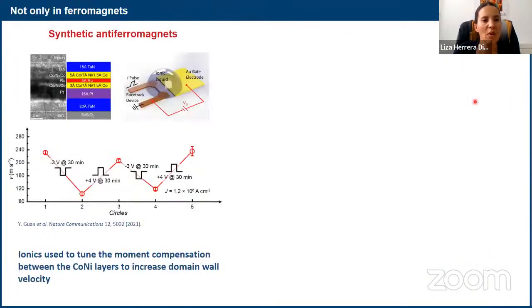Also another thing that is important to know is that this is not only in ferromagnets. We can find examples of magneto-ionic control in other types of magnetic systems. In particular, for example, here are synthetic anti-ferromagnets. This is done by a group in Halle. They showed before that this is a synthetic anti-ferromagnet, with these two layers coupled by the ruthenium, and they could show in earlier work that having this anti-ferromagnetic interaction is incredibly beneficial for the domain wall velocities in the system, and that it depends on the degree of compensation. So here what they did is that they simply took that type of system and put an ionic liquid on top, and by changing the degree of oxidation of the top layer, they could actually control the degree of compensation between these two layers. And this could create, as you can see here, really large changes in the domain wall velocity.